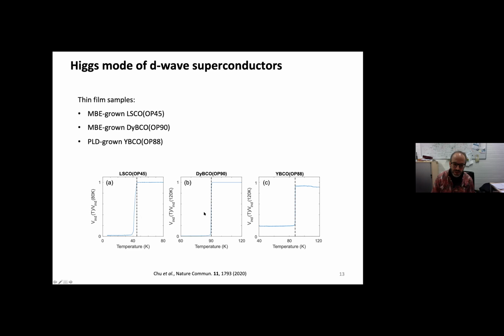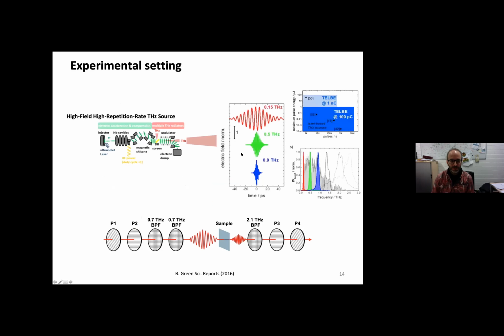And you see here, these are high quality thin film samples with very sharp and high TCs for the respective classes of these cuprates. And our experimental setup is here. So we are going to this high field terahertz TELBE source at the Helmholtz Center Dresden. And then we are tuning this undulator now to 0.7 terahertz in our experiment. And then we set up an experiment that we have full control of the polarization state. We also clean up the beam with bandpass filters. And then we go with a long multi-cycle 0.7 terahertz beam to the sample, and then we want to perform spectroscopy on potential third harmonic generation of the system, and also there we can map out the full polarization state of these generated lights.